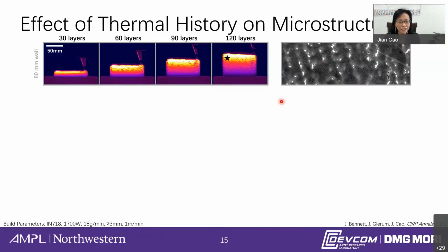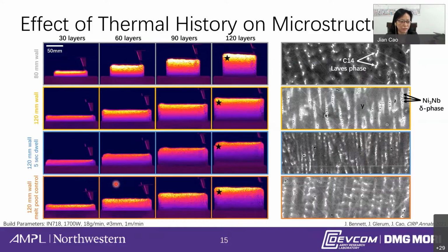So let me give you a little more detail by looking at the micrographs. If you look at, for example, this 80 millimeter wall at different build heights, this is the micrograph, and I'm just going to show you all of this and then talk about them collectively. You can see that the spacing of this is closer, which corresponds to the higher solidification rate. And the solidification band drives the grain size. Therefore you have a much finer microstructure with a 5 second dwell because you allow the material to cool down much more rapidly, right?